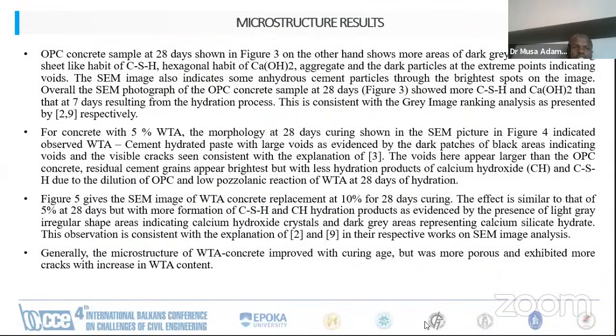Then the OPC at 28 days, shown in figure 3, on the other hand, shows more areas of dark gray particles indicating sheet-like habit of CSH. The SEM image also indicates some anhydrous cement particles through the brightest spots in the image. So we can say that overall, the SEM photograph of OPC concrete at 28 days shows more CSH and calcium hydroxide than at 7 days.